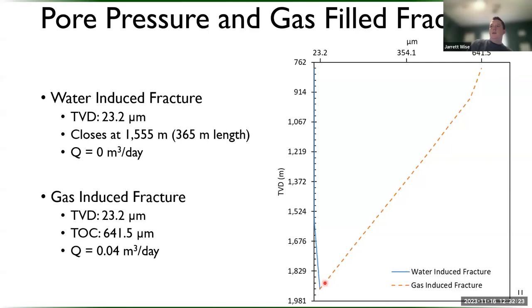So if you start to get a fracture down at the bottom and you have a gas source, it's able to really just grow that microannuli all the way to the top of the cement, creating a full leakage pathway, which is something that hasn't really been seen before in the academic stance.